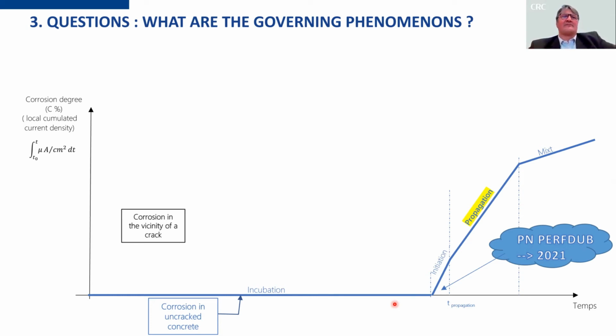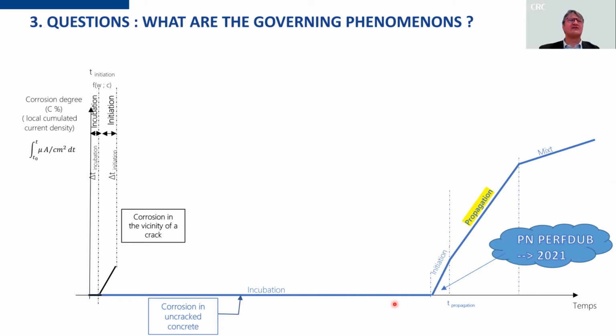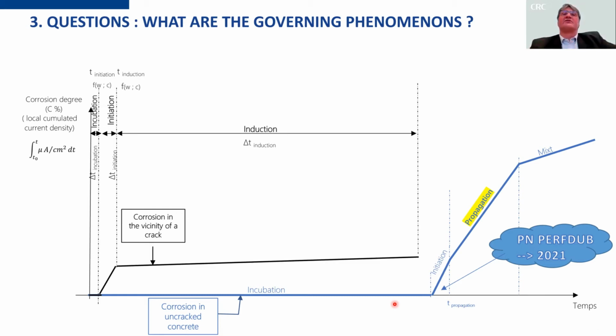When you have a crack, first you have a very short incubation period. Then you have the initiation, corrosion starts. And corrosion starts locally at a very high speed, I mean, in terms of density of current, not in terms of global current. And then you can have lots of phenomena, clogging of your cracks, and the corrosion almost stops. And after a while, the corrosion products, the aggressive products arrive through the concrete, and then you start the propagation.